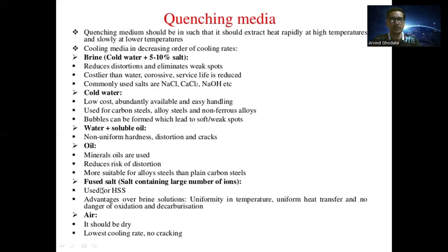Fused salt contains a large number of ions and is used for high speed steel. Its advantages over brine solution include uniform temperature, uniform heat transfer, and no danger of oxidation and decarburization. Air is the next quenching media — it should be dry air — and has the lowest cooling rate with no cracking.